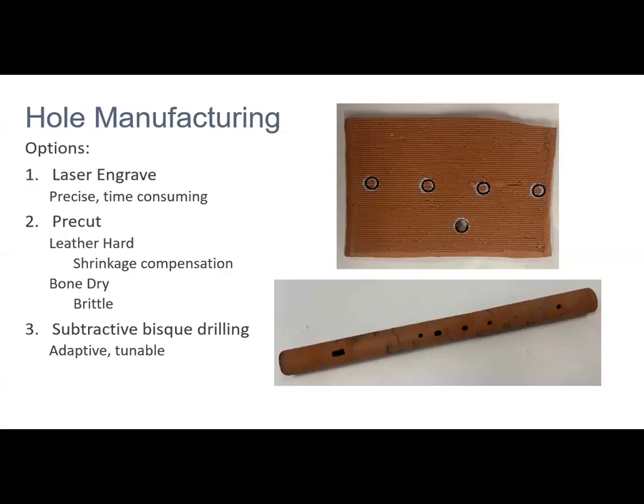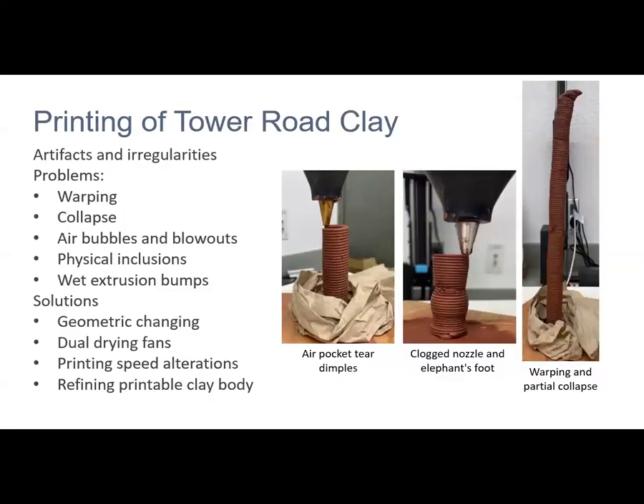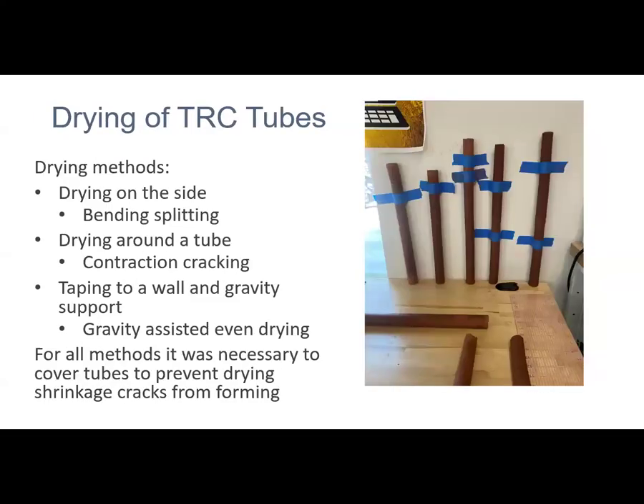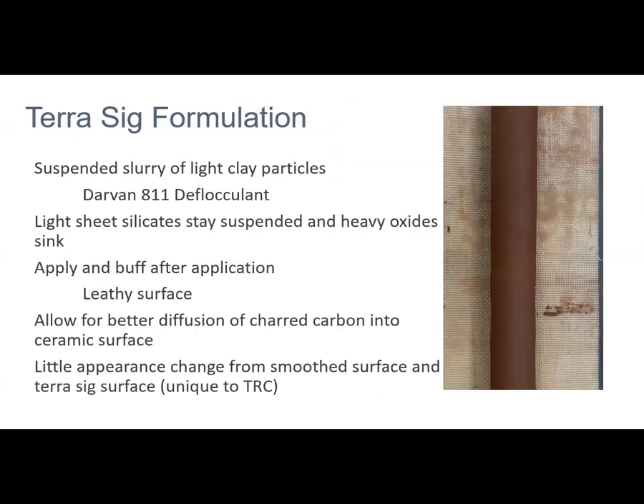When they fired a couple of them, after they were fired, they were a little bit too brittle to work on in some cases, and then with the bone dry, we had some collapsing. So after they put these in the kiln, they still had to cut, and there were a lot of failed ones through that process too. I don't want to spend too much time on this.